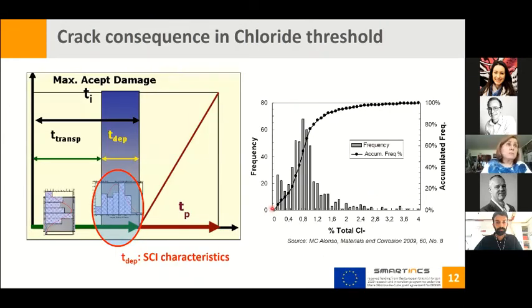But now we need another parameter, that is the chloride threshold. For the chloride threshold, we are thinking in the moment of the depassivation, and to determine this time to depassivation, we identify the amount of chloride that we need to initiate corrosion. Analyzing the literature data, we observe that there is a large variability, as I commented, mainly at the level of 0.8 percent of total chloride to initiate corrosion. Although the standards consider the value of 0.4 for new structures, and in some standards, they consider the value of 0.6 when thinking in service life for corrosion initiation. There are very few data in the case of cracked concrete, and some of them indicate really a clear decrease in the chloride threshold for corrosion initiation.